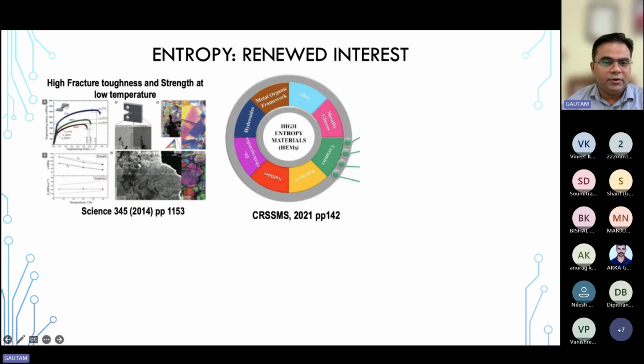So a paper was published in 2014 in Science, where they showed that if you take these particular alloys and carry out their fracture toughness at liquid nitrogen temperature, they found that as you go to the lower temperature, fracture toughness seems to be increasing, while the strength is also increasing at lower temperature. So this was something very remarkable, because as we know in metallurgy, as what we have been taught, strength and any kind of toughness or elongation are inversely related to each other, except in grain boundary refinement. So this is something which we are taught in our undergraduate.